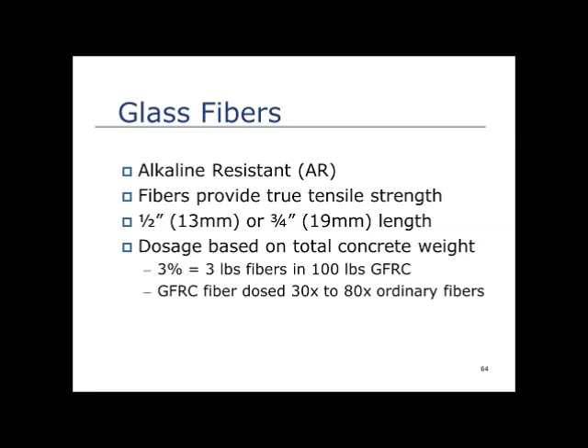Now, if you're familiar with the way, say, pigments are dosed in concrete, pigments are an admixture. So superplasticizers are admixtures. Air entraining agents are admixtures. Retarders are admixtures. Admixtures are always dosed relative to the cement content in the concrete. So if you have 3 pounds of pigment in 100 pounds of cement, you'd have a 3%, 3 per 100 dose of pigment. GFRC is not done that way. The fibers are not dosed. They're not an admixture. It's a very bizarre way of dosing, but that's just the convention.